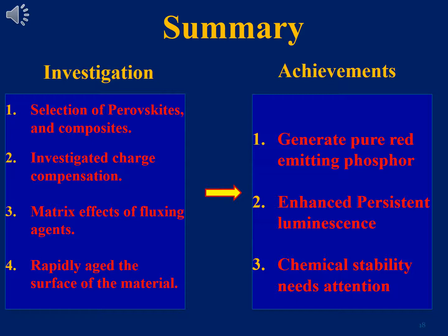To sum it all up, I have undergone an investigation of selected perovskites and composites, and I've investigated the effects of charge compensation. I have also looked into the matrix effects of fluxing agents, or rather using charge compensators to try and enhance the persistent luminescence. And I have also investigated the chemical stability of my material by rapidly aging the surface using an electron beam and backfilling with oxygen.